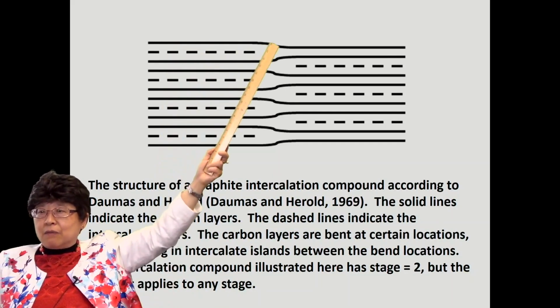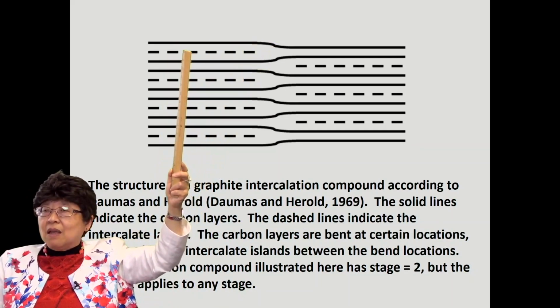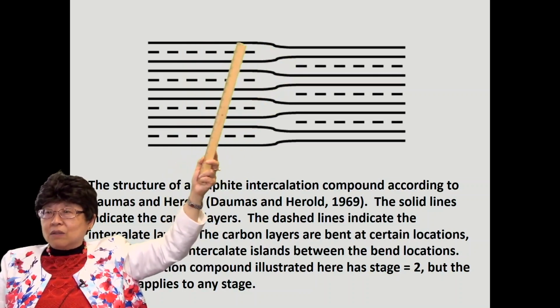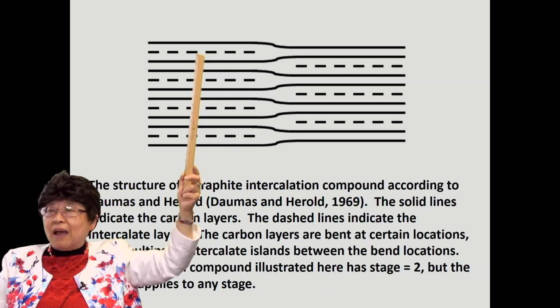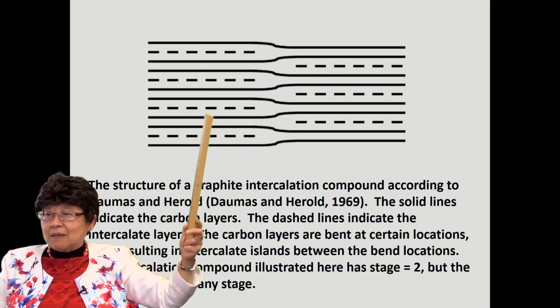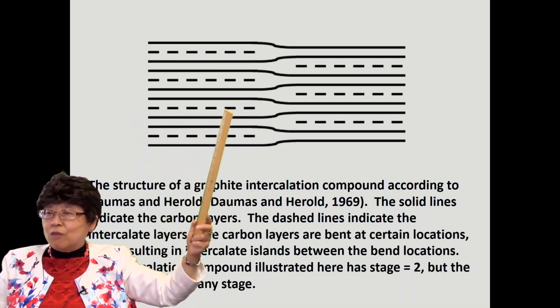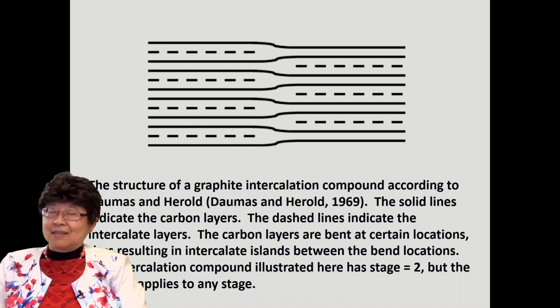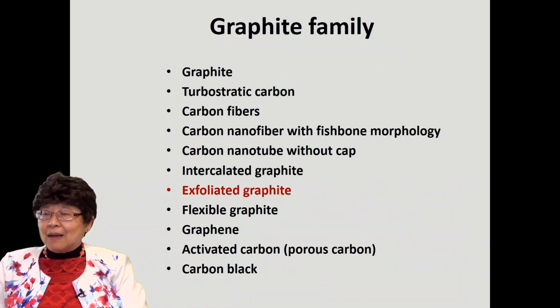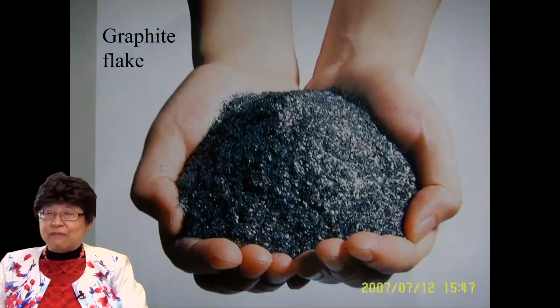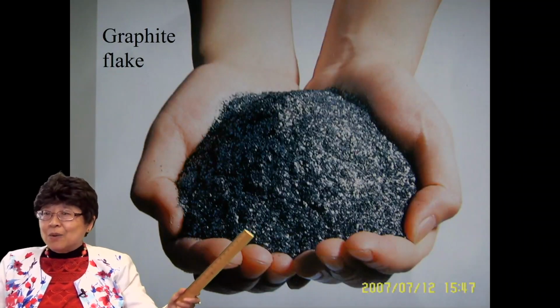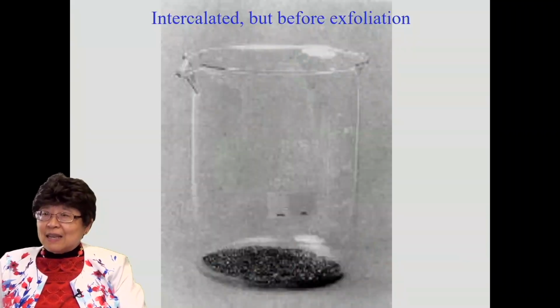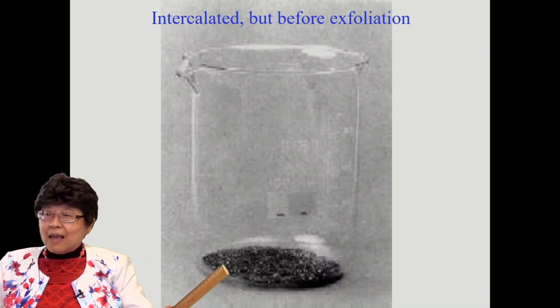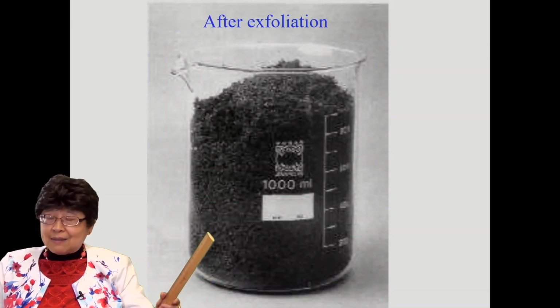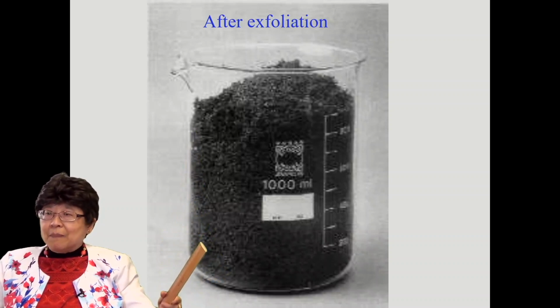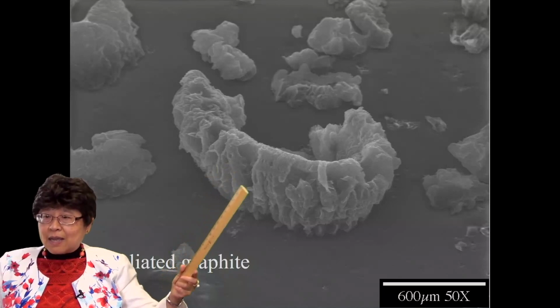The carbon layers are the full lines, and the intercalate layers are the broken lines. And the carbon layers are a little crooked here, and as a result, you have the intercalates in limited extents, forming an island. So you have intercalate islands, and that brings us to exfoliated graphite, which makes use of these islands. So in exfoliated graphite, you have graphite flake, and you intercalate the graphite flakes, and then you heat it rapidly, and it expands, and we call that exfoliation. It's puffed up, and this is how it looks after the puffing up.